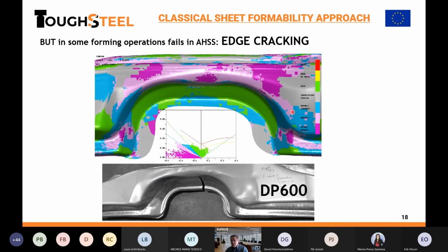This is an example of a part where all the modeling, all the simulation points in this area are below the FLD, so it's supposed to be in safe conditions, but we definitely see a crack. So this is what is called edge cracking. The cracks appear from the edge and grow through the material, and cannot be predicted by conventional sheet forming approaches.